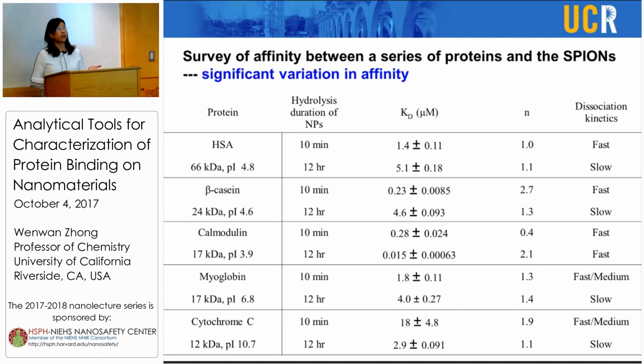For example, for human serum albumin, the one hydrolyzed for 10 minutes obviously has a very fast dissociation rate during separation, and we can only observe a mobility shift. But the one hydrolyzed for as long as 12 hours shows a very slow dissociation rate. So a very small head group difference already causes this kind of binding strength and kinetic difference, which was a big surprise to us.